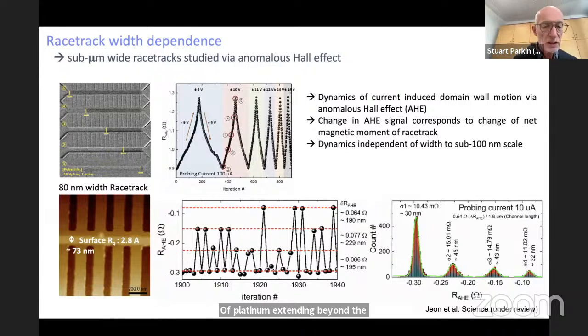And this wing, depending on how you engineer it, allows us to measure the position of domain walls, which are up to 20 times as far from the Hall sensor as the width of that wing. So this is really interesting as a means of detecting domain walls anywhere in the racetrack. So we can have multiple Hall sensors or just one, or we measure up to 16 in our experiments as shown in the top left.